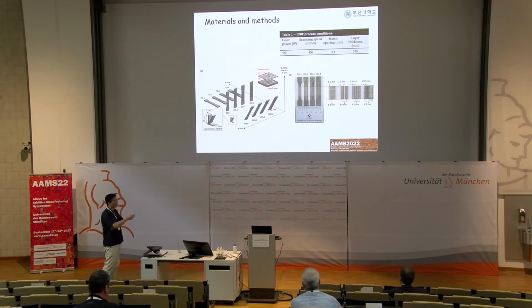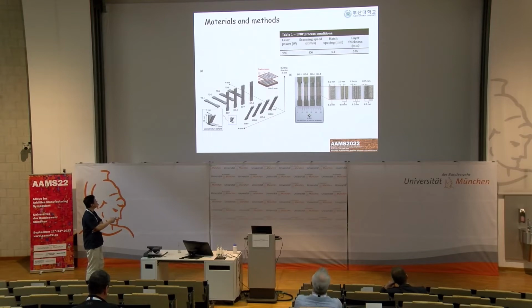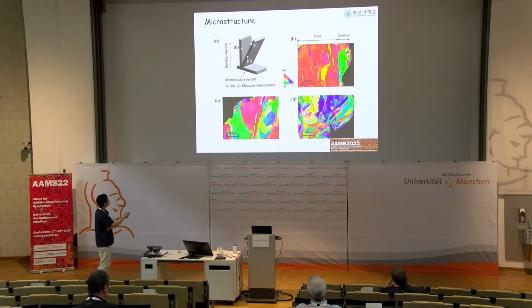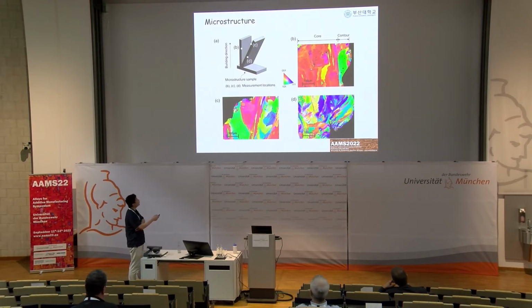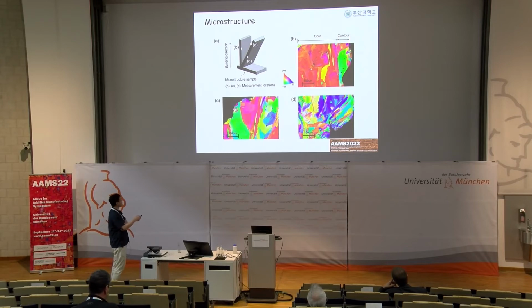If the contour scanning has some influence on the microstructure, then we are basically increasing the area that is influenced by the laser contour scanning. We produced samples in 3 different directions: horizontal plane, vertical plane, and 60-degree plane to the building direction. And we produced another small sample for the microstructure investigation. And here it is, the EBSD microstructure clearly shows that we have a slightly different grain structure near the contour in comparison to the core, and in the vertical direction, and also in the case that we have upskin or downskin.